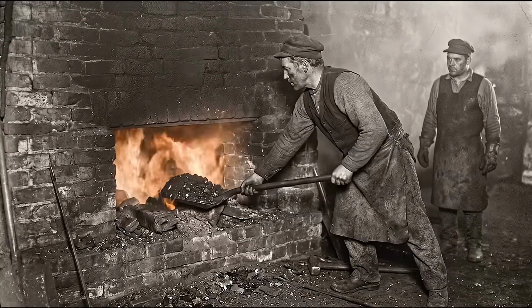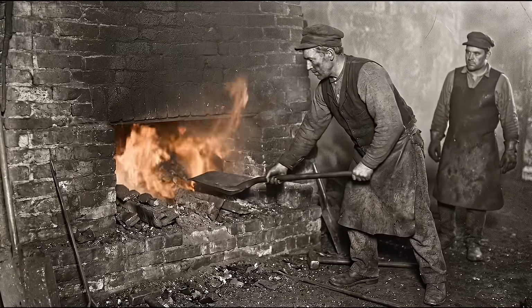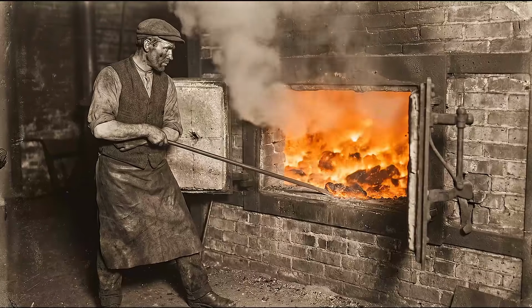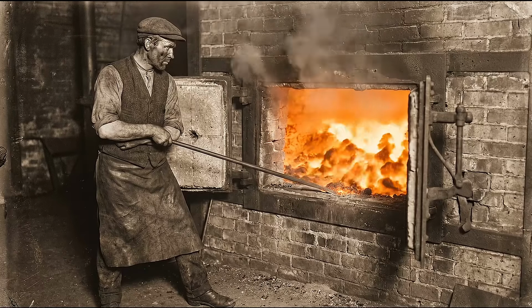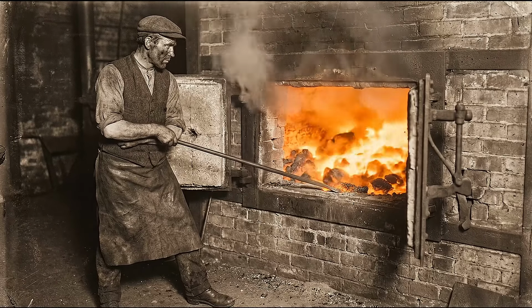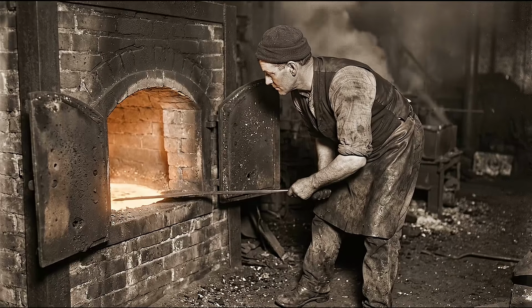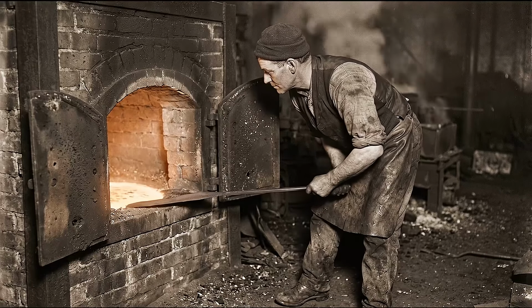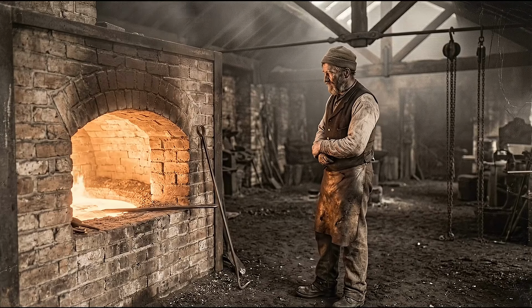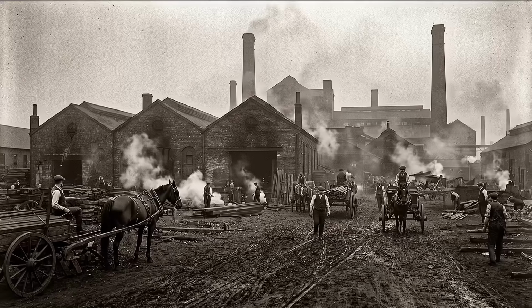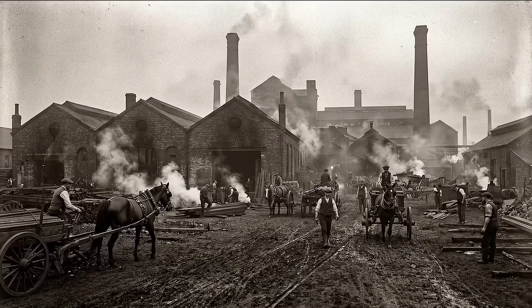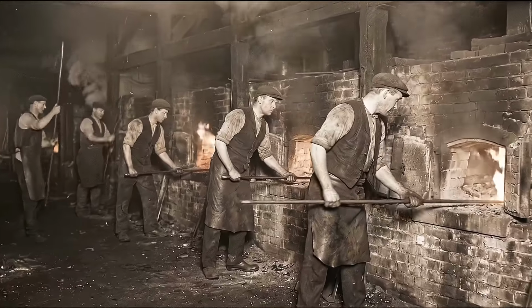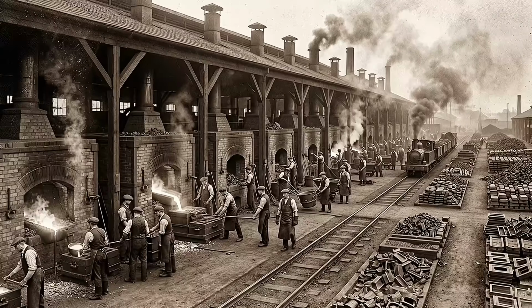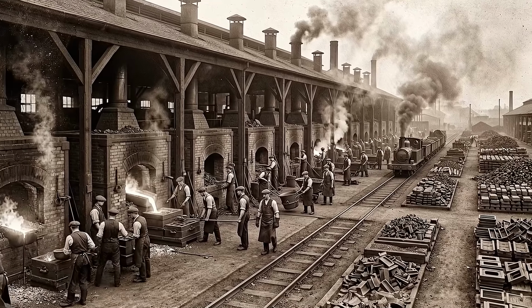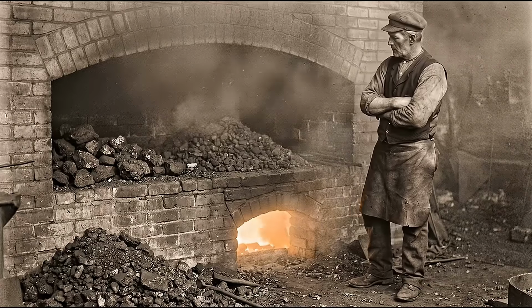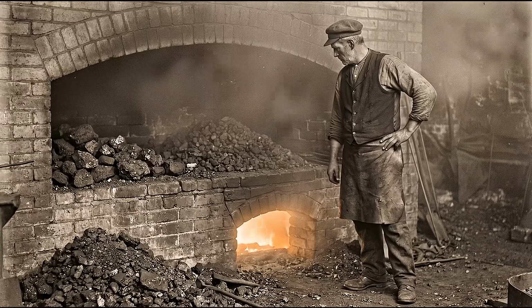Hall discovered that adding iron oxide, specifically a waste material called tap cinder, to the furnace charge caused the whole mixture to boil violently as the extra oxygen attacked the carbon. The boiling looked alarming, but once it settled, the iron that came out was cleaner and more consistent than anything Cort's original dry puddling had produced. Hall established the Bloomfield Ironworks at Tipton in the Black Country, and within a few years, this new approach, called wet puddling, had become the standard method across Britain and then across Europe. Cheap iron from low-quality ores could now be refined into perfectly serviceable wrought iron.